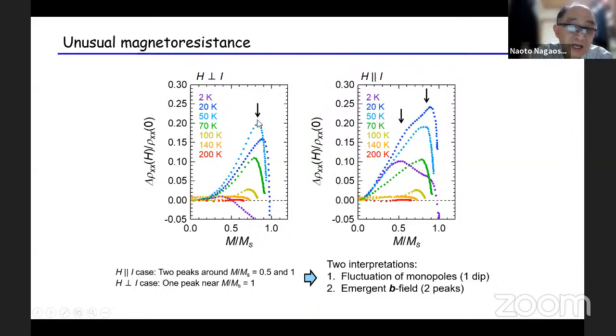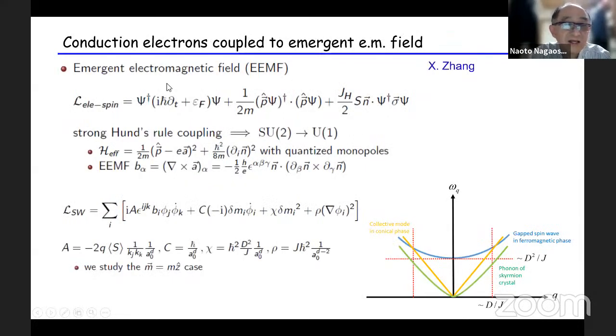And experimentally, there is some signature in magnetoresistance. So here is some peak structure, which almost corresponds to the annihilation of the monopole and anti-monopole. Then we try theoretically, this is again the repetition of gauge field scattering because the story is quite similar. Because you have a noncollinear or noncoplanar spin structure in the background, its fluctuation will lead to the fluctuation of the small a. So then this small a will scatter the conduction electrons to give a resistivity. But in the case of this chiral magnet, the fluctuation is not the Maxwellian gauge field, but the spin wave is the origin of this small a fluctuation.